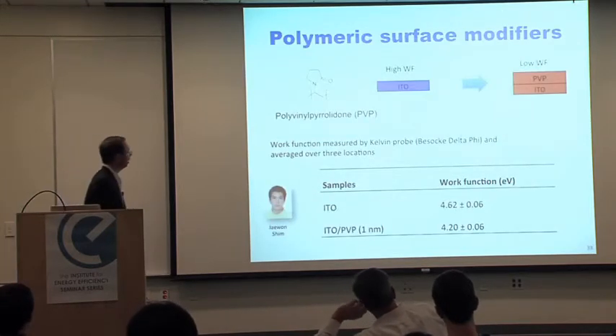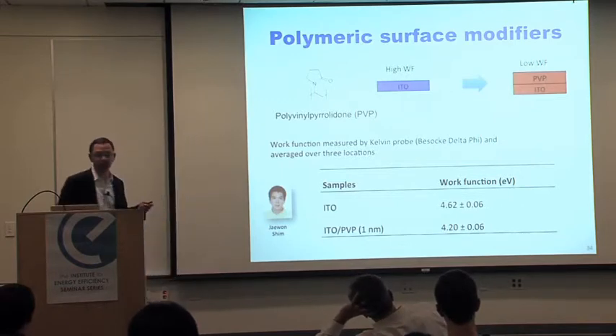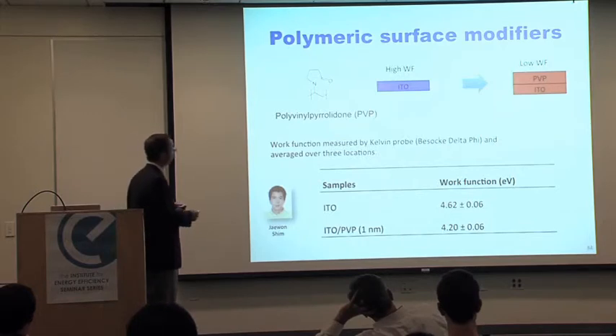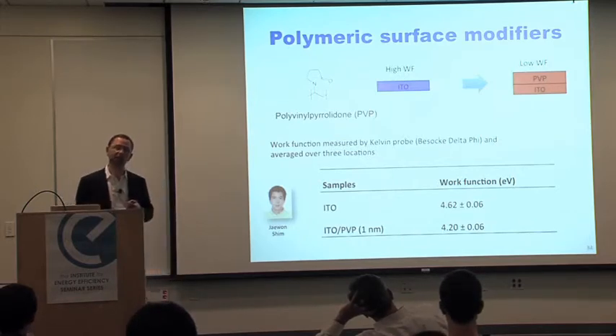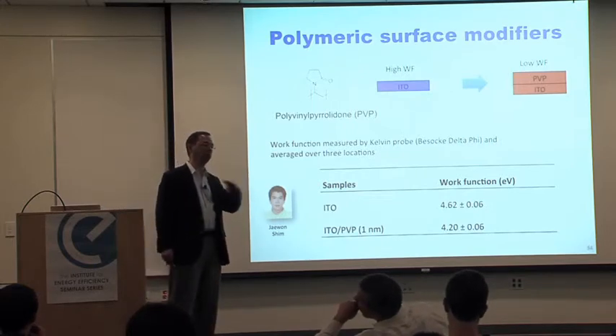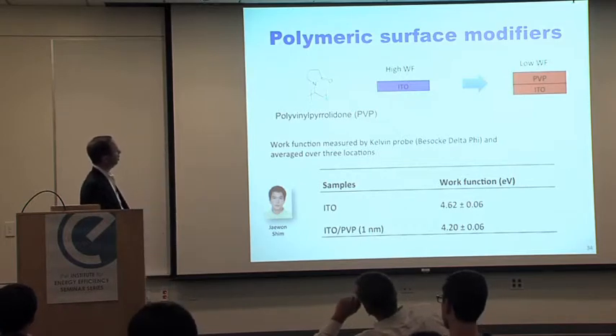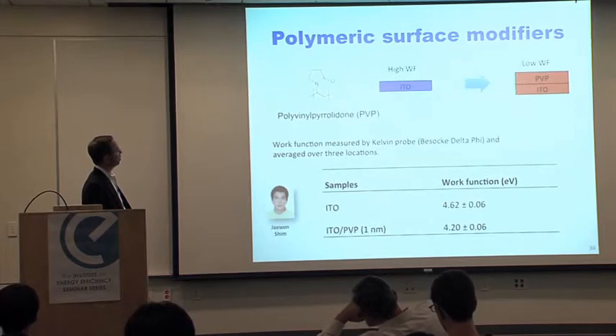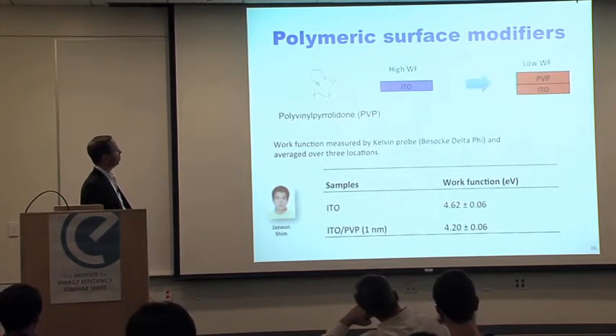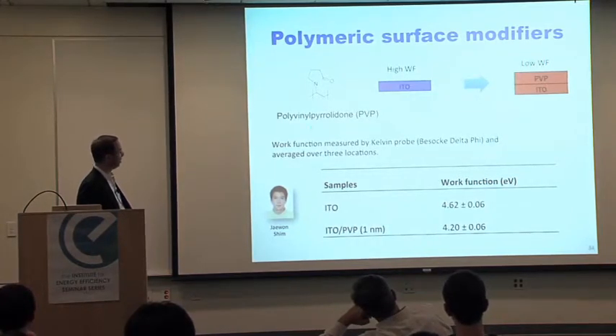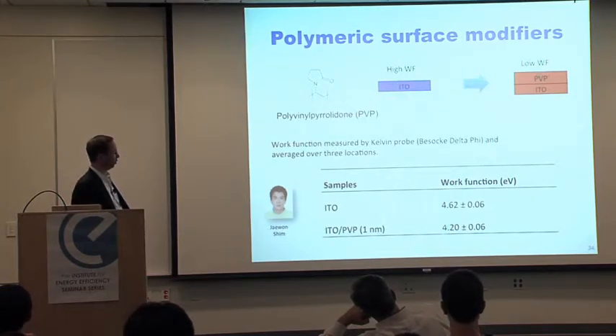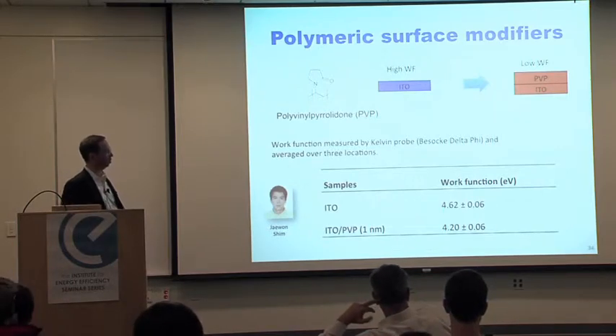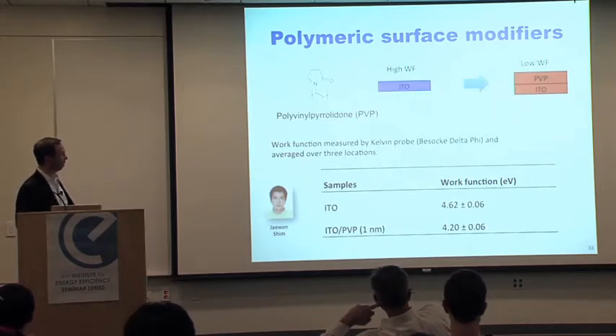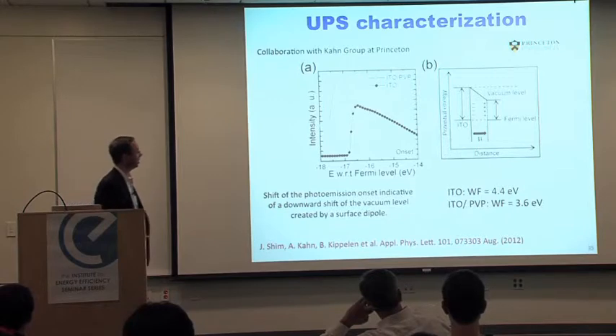And so by serendipity, one of my students, Jaewon Shim, actually came across a very interesting observation. He was using that compound shown here, which was a surfactant, because he was making solar cells where he was trying to fabricate a TiO2 layer for electron collection. And he observed that the more surfactant he was using, the better the solar cell. At some point, I asked him if he had tried to just use the surfactant by itself, and he had not, but he went back to the lab and just dipped ITO into a dilute solution of that compound, measured the work function of just clean ITO and ITO coated with that PVP, and he saw a significant reduction in work function.